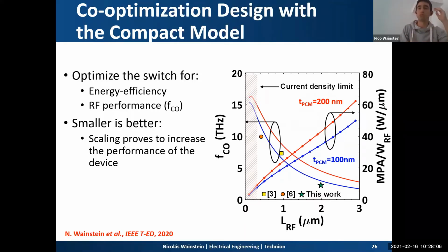An important conclusion of this work is that for the case where the heater width and the RF gap are equal, scaling improves the RF performance. You can see here in the left axis the cutoff frequency, that's the figure of merit in terms of RF performance, and it will also improve the switching power, which is determined by the minimum power for amorphization, that is the MPA.